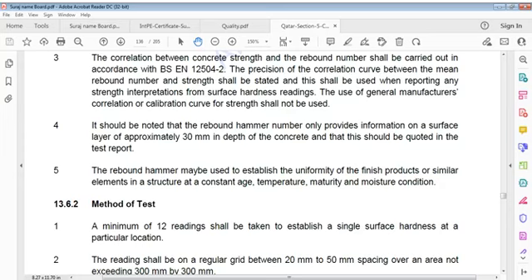Use of general manufacturer's correlations or calibration curve for strength shall not work in that case. It should be noted that rebound hammer number only provides information on a surface layer of approximately 30 mm in depth. 30 mm, only 3 cm in depth of concrete, and that this should be quoted in test report.